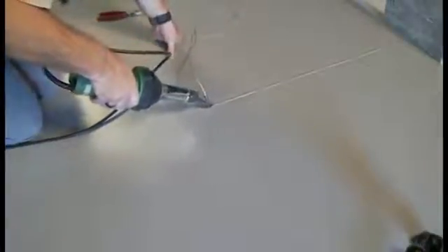When welding commercial vinyl sheet flooring, it is important to use a narrow tip nozzle and proper speed to prevent burning of the material. When properly welding commercial vinyl sheet flooring, you will be able to see a ridge building up on both sides of the weld rod. This will ensure a properly welded seam.